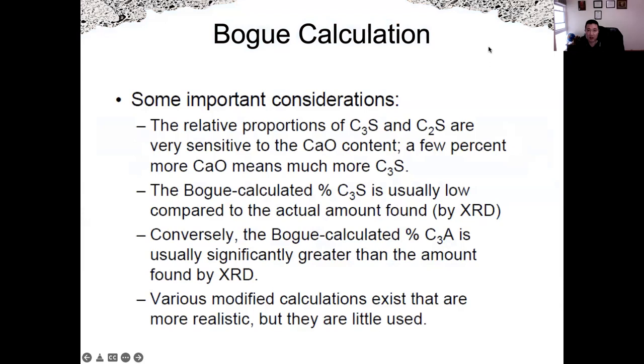So here's some consideration about Bogue calculation. The relative proportion of C3S and C2S are very sensitive to calcium oxide content. A small percentage of difference in calcium oxide will affect the calculation quite a lot. And the Bogue-calculated percentage of C3S is relatively lower compared to using other methods such as XRD. And these are some notes about calculation of C3A percentage. Some other equations exist, but by far the most commonly used is this, the Bogue calculation.